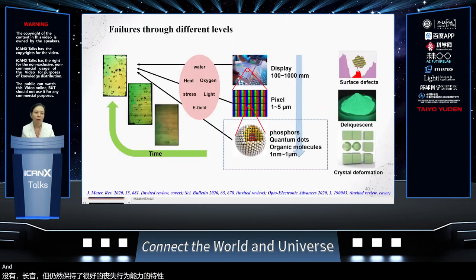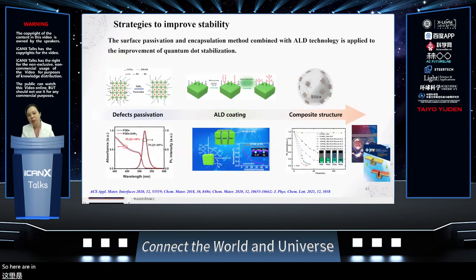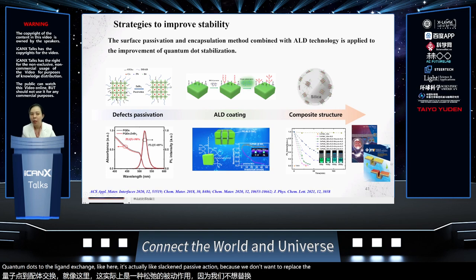And all of those were shown on the encapsulations, but many times the encapsulation is not only on the display or the microscopic ranges, it can actually go down to the pixels or even to the phosphor materials themselves. So here we actually passivate the perovskite quantum dots through ligand exchange. Here, it's actually like selective passivation, because we don't want to replace the ligands, but we want to passivate the points that haven't been covered.